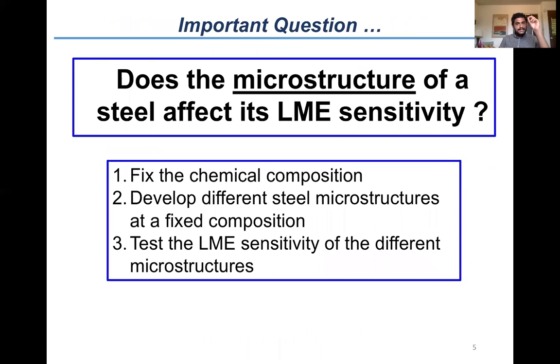We use a steel of a fixed composition. We develop different microstructures at the fixed composition, because we cannot afford to change the composition, because composition is an additional variable for LME. After we develop different microstructures at a fixed composition, we test the LME sensitivity of these different microstructures. So I'll take you through this process of how we did this.